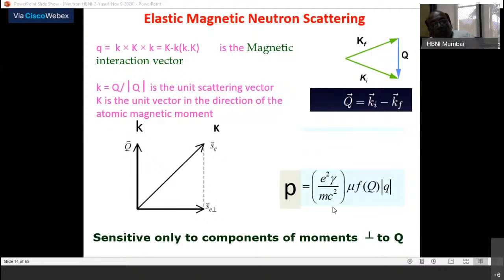So, you go to any synchrotron facility website, there are any number of activities on magnetic scattering as well. Because the charge scattering is stopped, that intensity does not go to the detector. What the detector measures is only the magnetic scattering part. Though in a relative sense it is 4 orders of magnitude weaker compared to the electric field scattering, since the incident flux is very, very high, that so-called weaker component is still a measurable quantity because you have filtered out the charge part by a suitable analyzer.